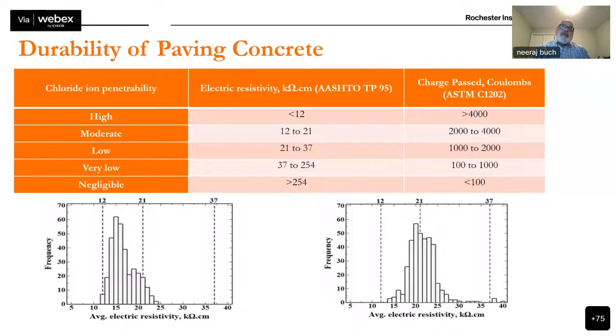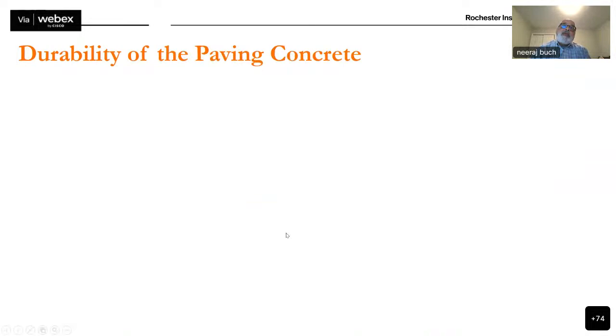So the higher the resistivity, the lower the permeability; the lower the resistivity, the higher the permeability. That's just how you look at this table. And both I-69 and US-131 concretes were within very low to moderate levels of permeability, which is what you're looking for.